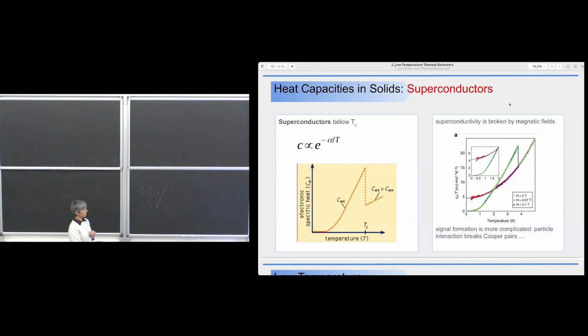And then, experimentally what we have seen is that when you have particles that interact in the superconductor, you have to deal with the quasi-particles that are broken. And this implies that you have non-ideal behavior of your detectors. And so generally we avoid using superconductors. And moreover, superconductivity is broken by magnetic field. And therefore, you have to operate your detector using a magnetic shield in order to avoid any kind of interference that leads your detector to change behavior when you have magnetic fields that are changing around, or when you have the Earth magnetic field that is interfering. And so they are not used.